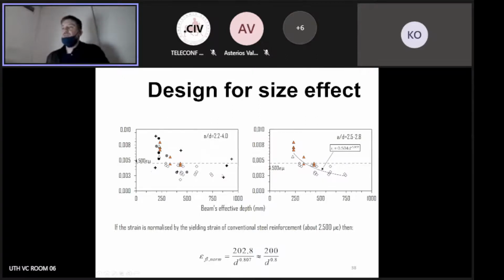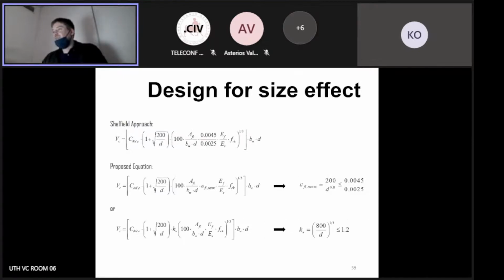So here we have a set of data where red triangles are my data from my PhD. I dug a little bit deeper and also found some other research studies where people were testing larger elements, and then excluded all the elements which were too slender or too much like corbels, and I really saw a quite clear trend that maximum strain in the longitudinal reinforcement should not be really a fixed value, but it's really a function of the effective depth of the beam. And when I worked on it a little bit, it showed that it can be easily applied as an additional reduction factor to the already existing reduction factor for steel reinforcement.